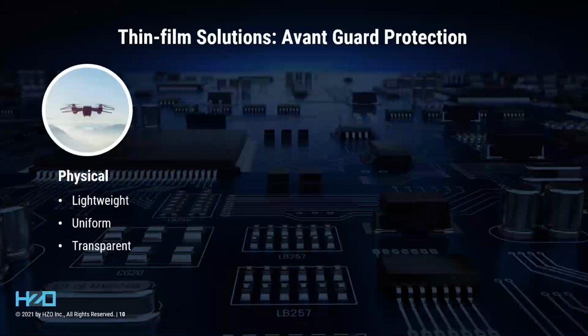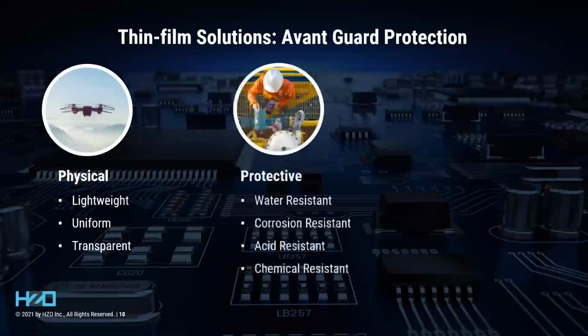They're uniform, both in chamber and on board. So you end up with a very highly repeatable manufacturing process. There's no operator variability, no differential wetting based on the temperature of the production floor. Because it happens in a vacuum chamber, it's always the same. They're either highly transparent because they're so thin, or they're optically clear. So a thin oxide layer is basically glass as far as we're concerned. So it tends to be a very good optically performing coating.